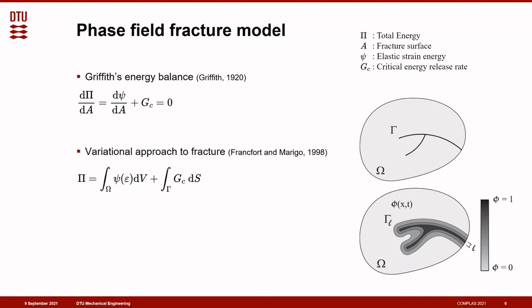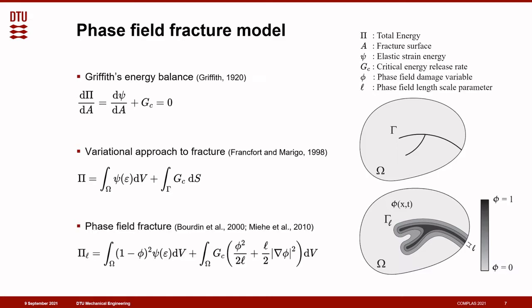One can formulate the Griffith's energy balance in a variational form. However, minimization of this Griffith energy functional is hindered by the fact that the crack surface gamma is unknown. And here is where the phase field paradigm comes to our rescue by transforming the surface integral into a volume integral. Two things that I want to emphasize here.